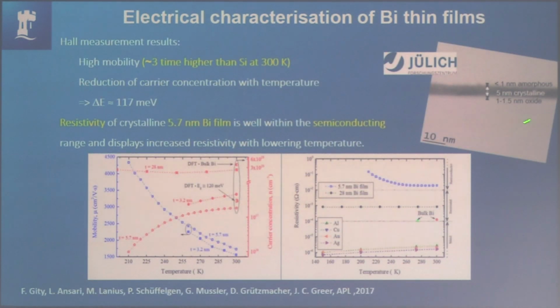So first thing is, here's an example of one of the layers they're growing that's 5 nanometer. There is a structural phase transition as you start to grow these, which is giving us some questions we can't answer. But anyway, what happens is we do 4-point probe measurements on these thin films, and you see some nice things. This here is the temperature dependence of the resistivity, which shows that it should be a semiconductor.